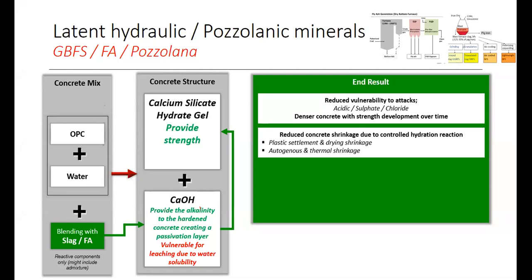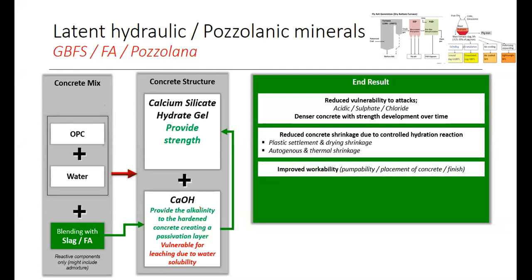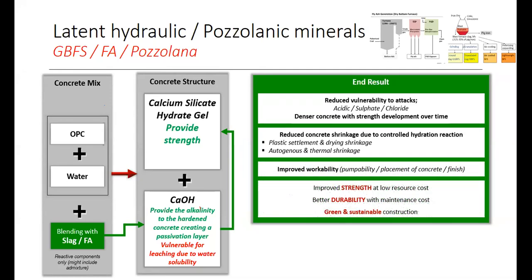Because of that, the cement is delivering less C3S and C3A, which are the main root causes of heat of hydration. By reducing those materials, they can reduce the heat generation, which is good for shrinkage and heat of hydration matters. And it improves workability, improves strength at low resource cost, gives better durability, and it's green and sustainable, because slag and fly ash are byproducts from other industries like the power generation industry and the steel industry.